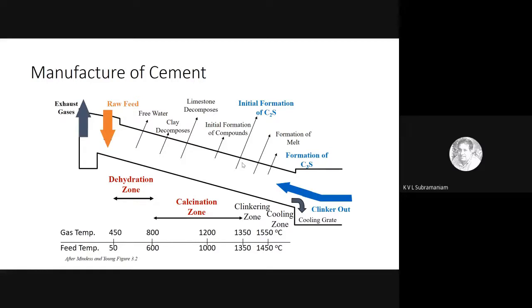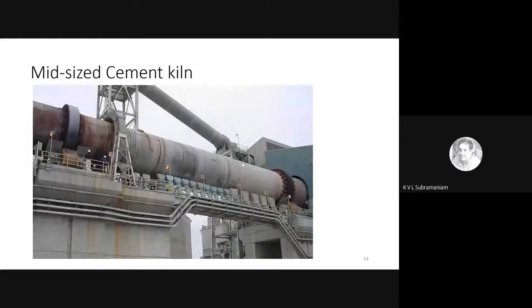So basically I get these primary silicates, which are C2S and C3S, that form as the charge is moving forward, moving through this drum, and eventually the clinker is discharged at the opposite end of the drum. So this is what a cement kiln looks like. This is a rotary kiln, and now the efficiency of the kiln has been maximized.